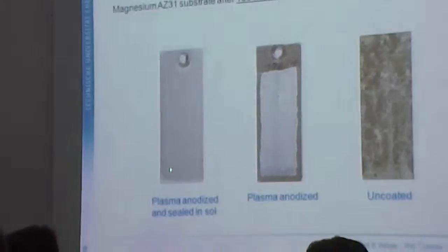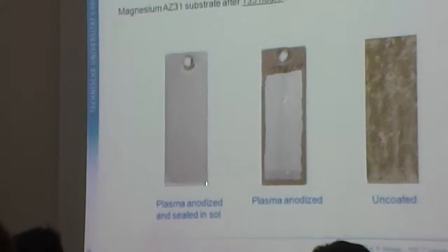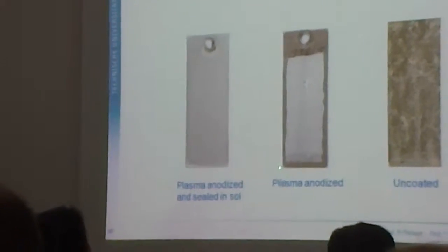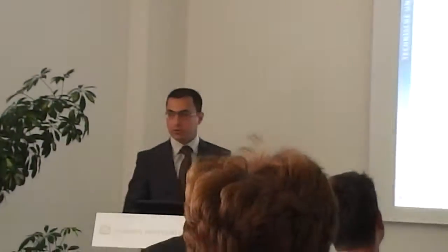The corrosion test showed this, the magnesium sample uncoated. For the plasma anodized magnesium, there are traces of corrosion, that's clear. And for the plasma anodized magnesium sealed in the sol, there are no traces of corrosion. Also at the corners, here the corners are covered because of the spray.